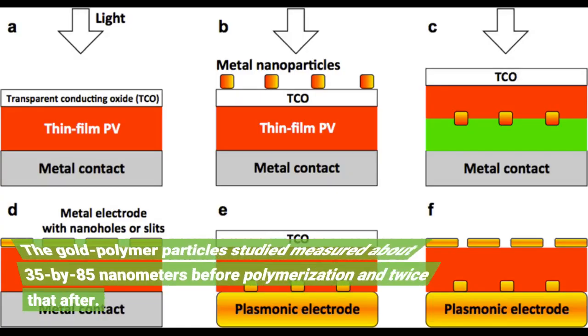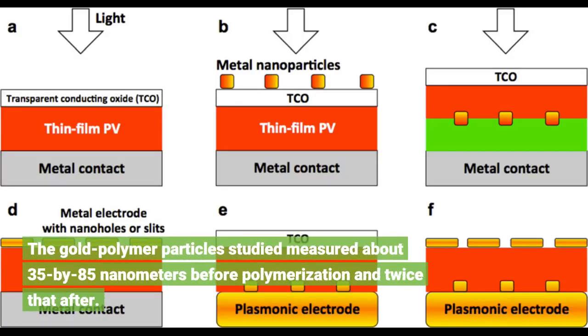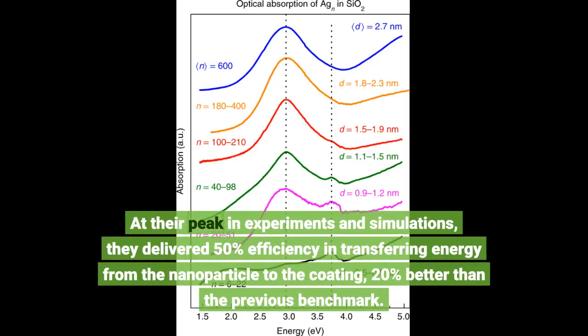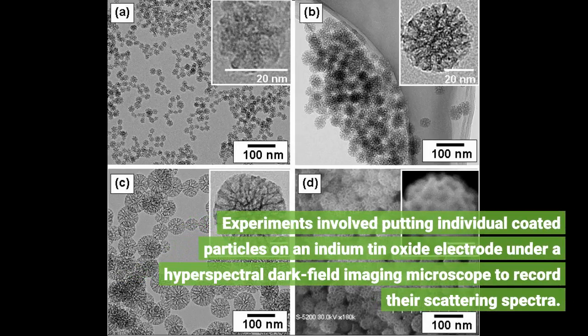The gold polymer particles studied measured about 35 by 85 nanometers before polymerization and twice that after. At their peak in experiments and simulations, they delivered 50% efficiency in transferring energy from the nanoparticle to the coating, 20% better than the previous benchmark. Experiments involved putting individual coated particles on an indium tin oxide electrode under a hyperspectral dark field imaging microscope to record their scattering spectra.